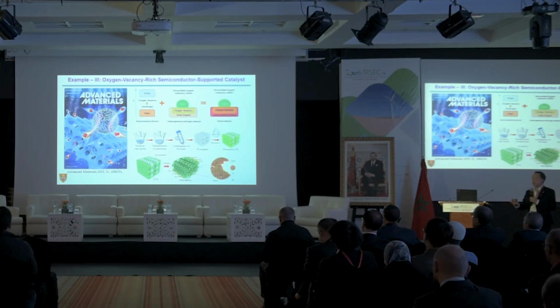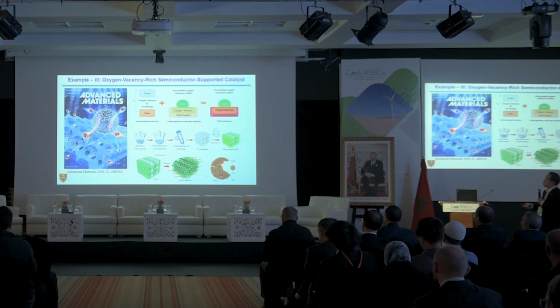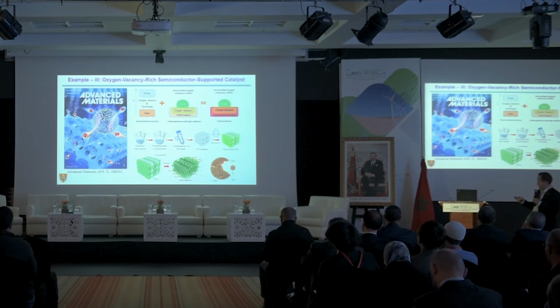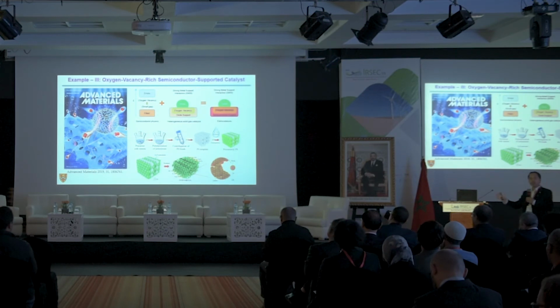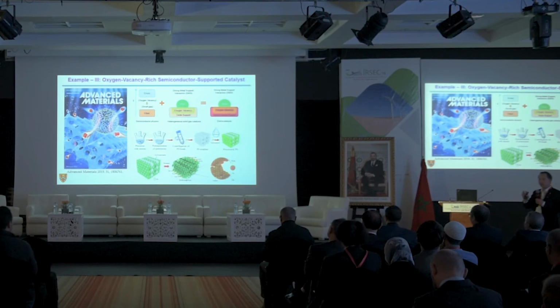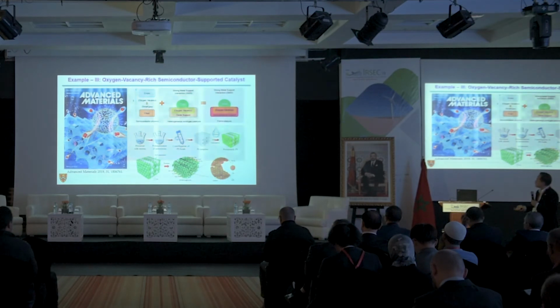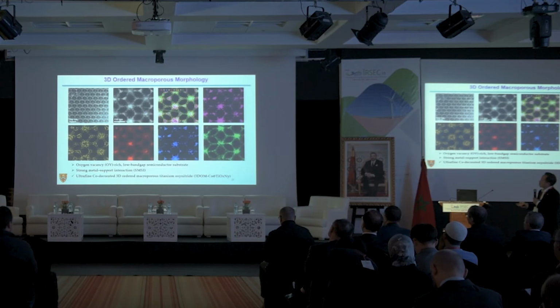The next step, actually, we try to go to three-dimensional, as we mentioned. So we designed the 3DOM catalyst. It has big pores, about 50 nanometers or 100 nanometers. You can design it depending on the templates you are using. You can control the PS bead size, then you can control the pore. So we can easily design a 3DOM catalyst, a micrometer-size catalyst with very good porosity inside, so that you have very good mass transport in the catalyst. That is our main purpose. You can see this pore is well controlled when you prepare the catalyst.